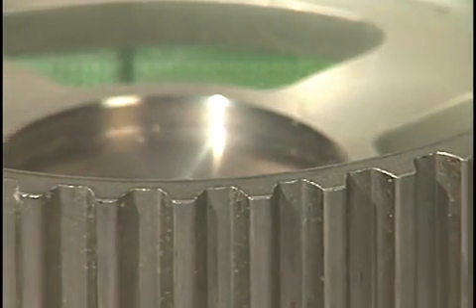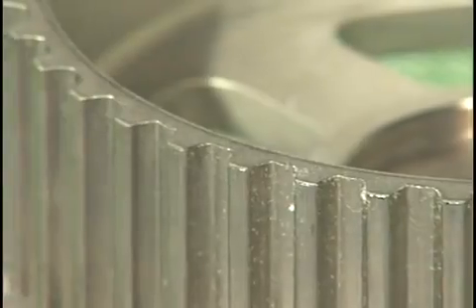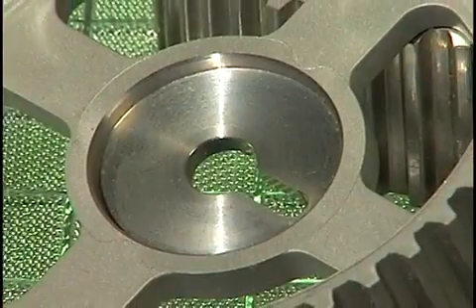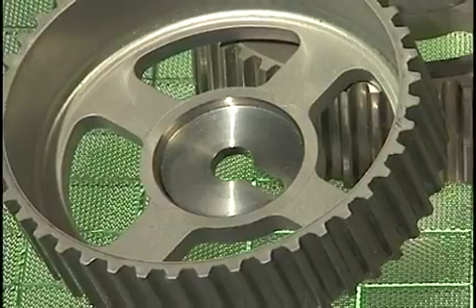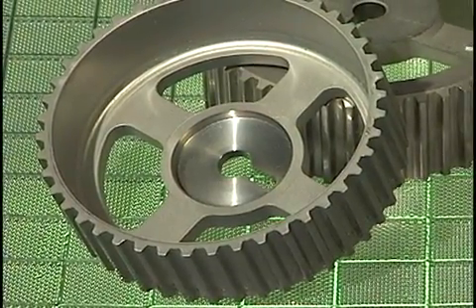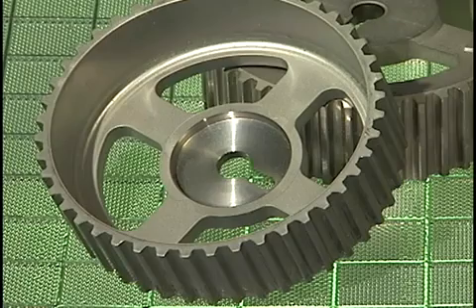21,750 psi. Successfully producing the large pulley required a special powder mixing technique of first coating the particles with a liquid binder, followed by the addition of a substantial amount of a special lubricant. These additives were completely removed by precisely controlled vacuum dewaxing. Machining the inner diameter counterbore is the only secondary operation.